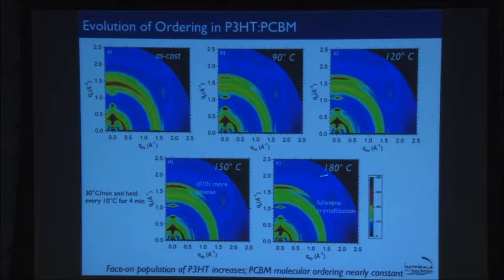Now, when I look at it, and I say to myself, what happens? Actually, the polymer, as we see here, the part that's oriented edge on, is getting a little more intense. But we actually see a big difference with the face-on portion. This peak here is becoming more intense. And so it actually is crystallizing. And it's OK, because the fullerene diffuses around very quickly. So when the polymer wants to crystallize, the fullerene just gets out of the way. It's got no trouble getting out of the way.